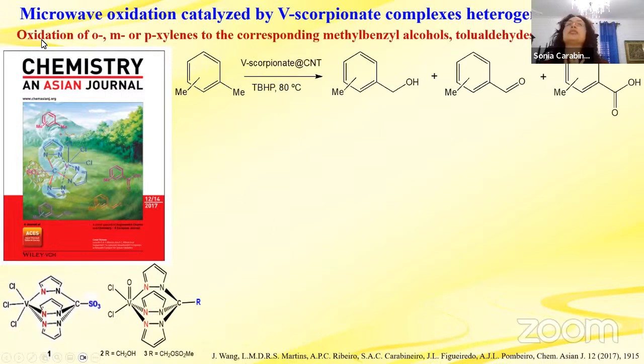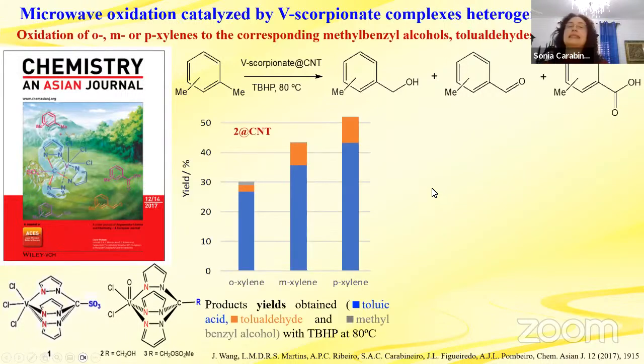And we tested the oxidation of ortho, meta and para-xylenes to the corresponding methylbenzyl alcohols, tolualdehydes and to toluic acids. So we tested these two vanadium scorpionate complexes, and the best results were obtained with this complex, number 2 complex, on carbon nanotubes. And we see here the yields for ortho-xylene, meta, and para-xylene. So it was better for para-xylene.